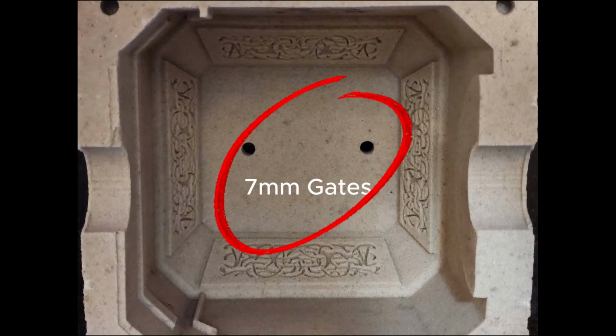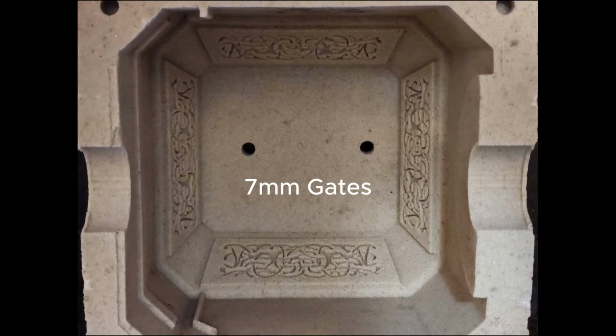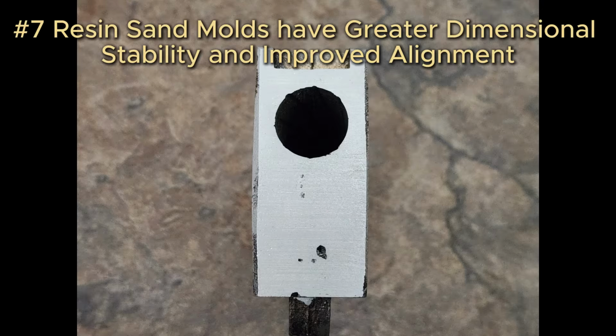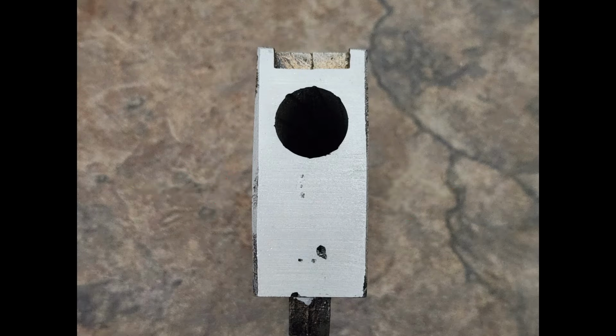Here's a mold I use for a massive casting, but it only has 2 7mm gates. Petrobond sand would erode and cause sand inclusions in the casting. Here's a photo of a casting done with Petrobond. See the bulging at the sides?